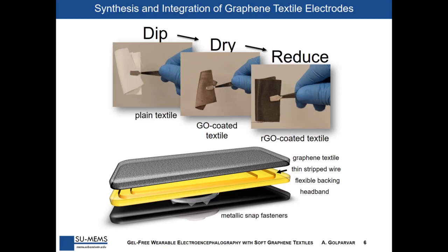Later on, for prototyping, the prepared e-textile piece was cut into a desired dimension and fixed on a flexible sticky foam, where it sandwiched an ordinary sports headband and a metallic snap fastener in order to establish electrical connection with the front-end circuitry. To acquire higher signal-to-noise ratio and ensure interference stability, we have also used elastic bands with Velcro straps and foam padding to provide pressure approximately in the range of a few millimeters of mercury to form a stable high contact area